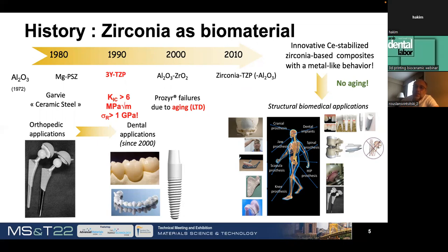First, we used alumina, but starting from 90s, we use 3% yttria zirconia. It was used up to early 2000 because what happened is that we noticed some aging issues with this material. What kind of aging issues? In fact, because of yttria, we create oxygen vacancies in this material, and under the impact of low temperature and water, which is typically the ambience, the environment inside of the human body, there is the degradation of the material, slow degradation, but degradation.